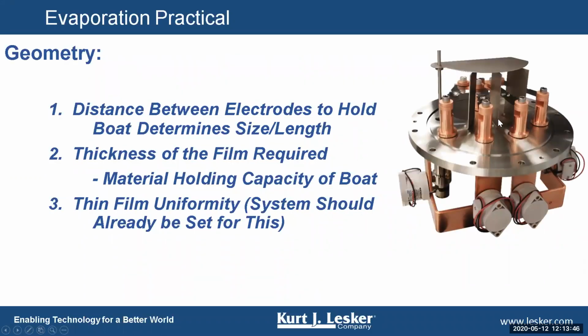Distance between electrodes. Here you see a cluster flange of 3 or 4 evaporation sources. And from post to post, the evaporation source spans. This length is critical to know because if you're ordering a new boat or reordering boats, it's important to get the right size boat here. Otherwise, you're going to wind up trimming down boats or adding extension plates to hold smaller boats.